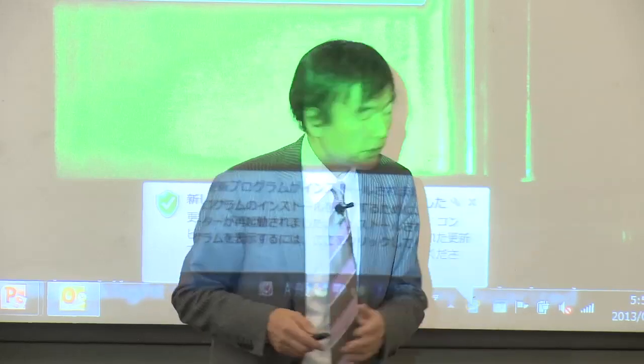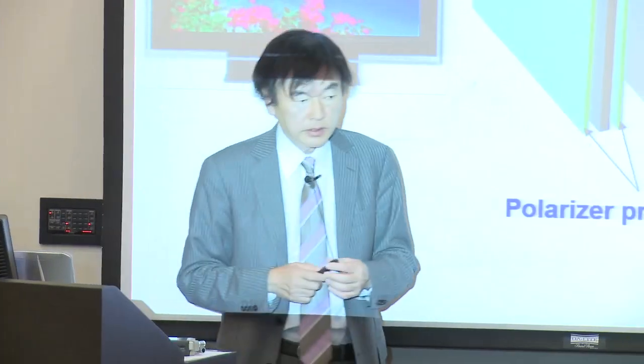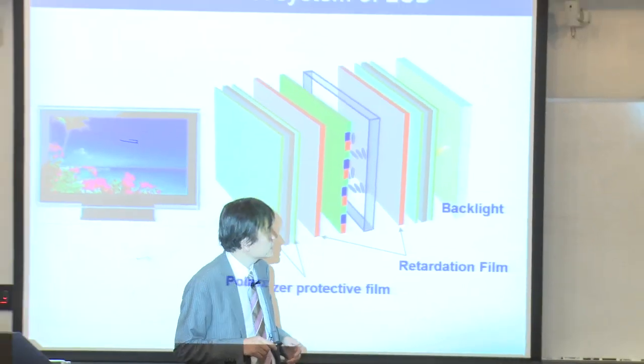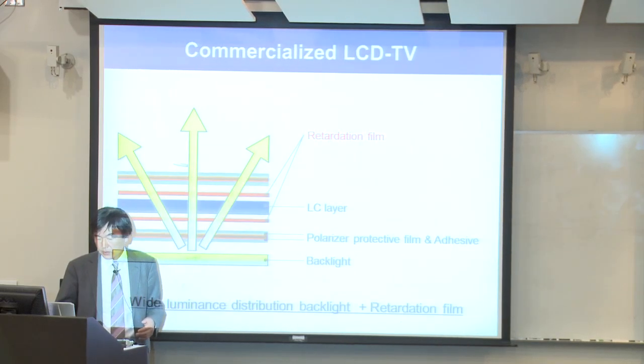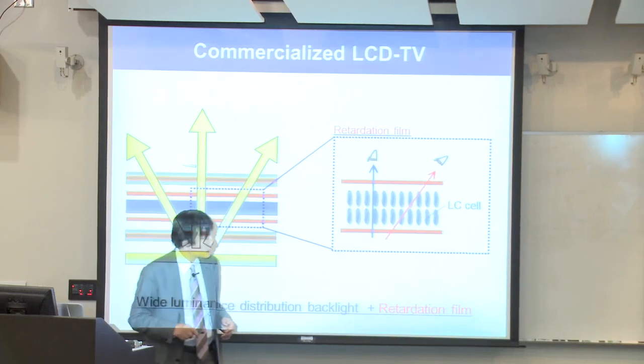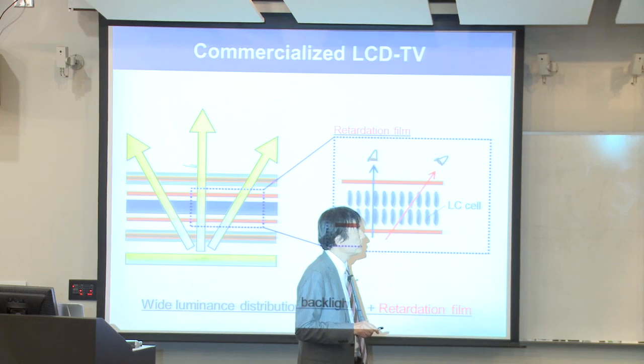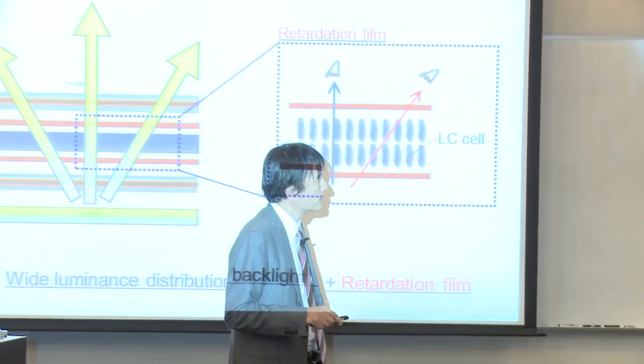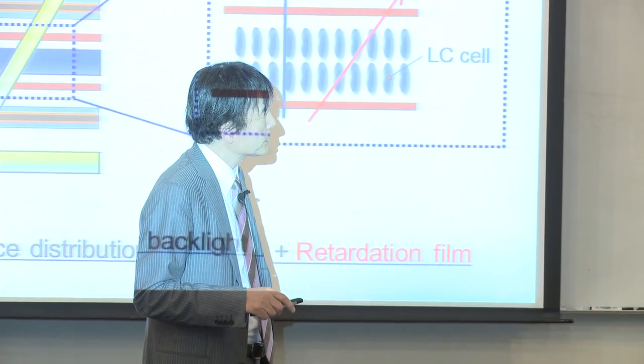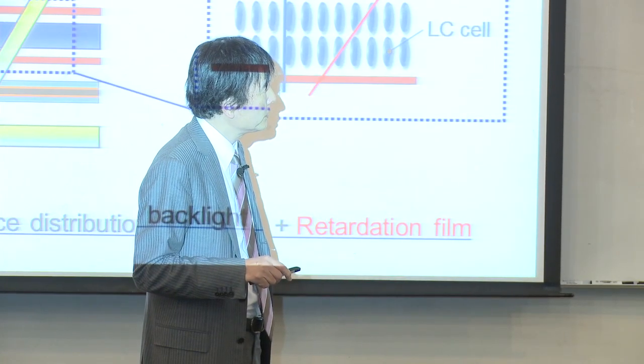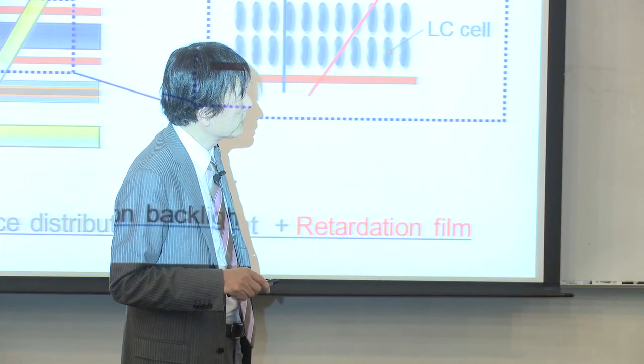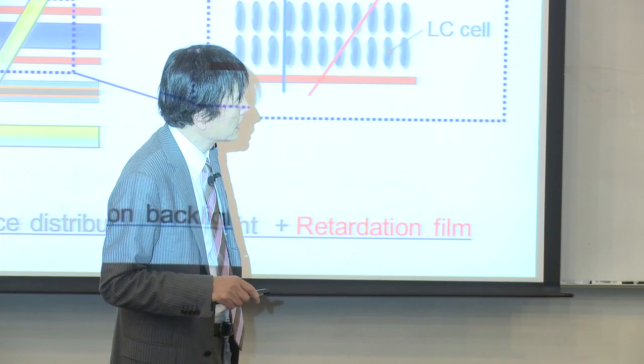So the problem of the liquid crystal display is the power consumption. So 50% is absorbed. But now with using this, brightness is achieved. This is the conventional liquid crystal display system. As you know, the light comes like this. The problem is the changing of the viewing angle. If we see blue here, but changing the viewing angle, it becomes red due to the birefringence of the liquid crystal cell. So in order to compensate this birefringence, retardation films are used here. But this retardation film is not ideal to completely compensate the birefringence of the LC cell. So some degradation of color uniformity is caused.